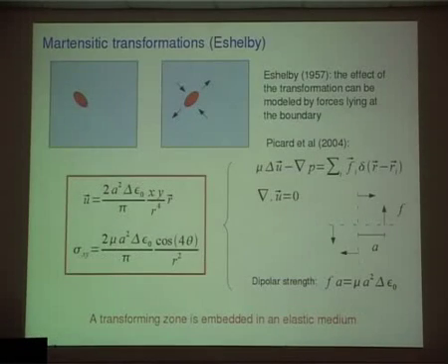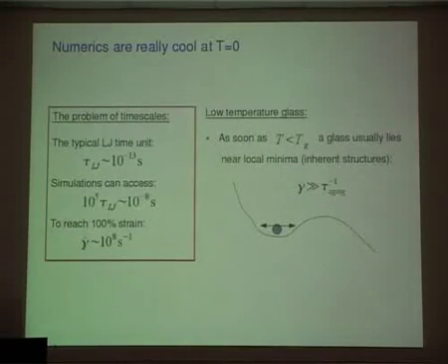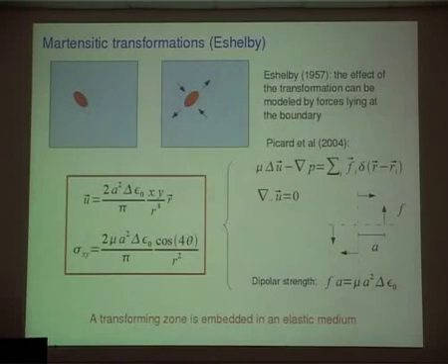And the big problem, which in fact comes from works on Martensitic transformation, is that we know that when a rearrangement occurs, it might couple elastically with the rest of the system. So, in fact, this is an idea which comes from Eshelby, and initially from Martensitic transformation. In the context of a Martensitic transformation, you have, say, a metal, and inside you have a change to Martensite, which is essentially a part of the metal which will rearrange because it's changing.